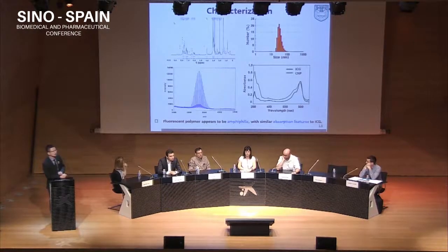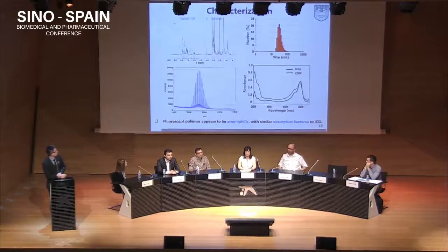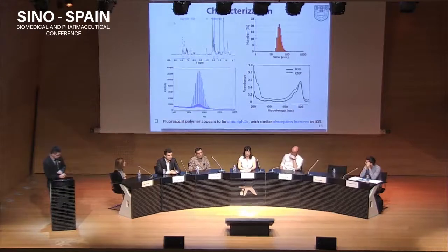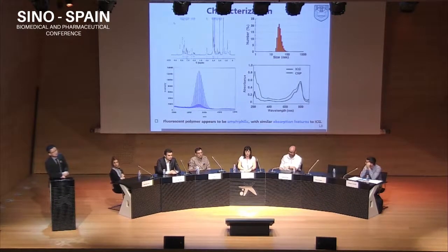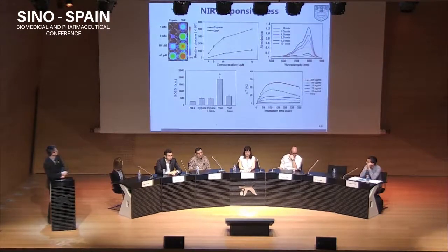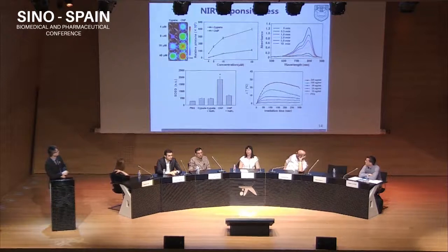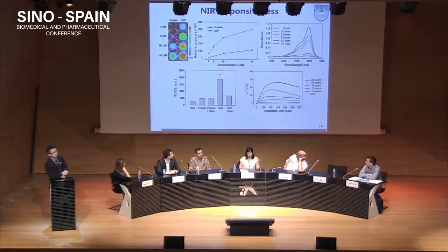After characterization, because the polymer is very amphiphilic, it can self-assemble into nanoparticles in PBS with a size of about 60 nanometers. And we found that our nanoparticle's absorbance resembles ICG, especially in the near-infrared range, with the same absorption peak, about 800 nanometers. With the same concentration of free dye and nanoparticle, interestingly, we found our nanoparticle shows much stronger fluorescence intensity compared to free dye, about 4-fold.